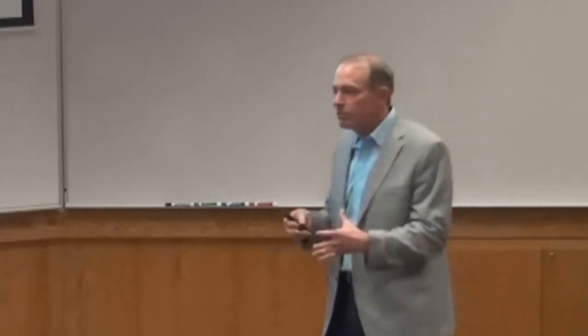The nice thing about this experiment is that it provides a one-to-one correspondence between what we can measure and what people can model. A lot of times when people do models, they have to upscale through several orders of magnitude. In this case, there's no wiggle room. What we measure is what they model. And so a group at Florida modeled this, and they got very nice results that compare very closely to what we measured. So we're happy about that. Although their paper seems to be getting referenced more often than ours.